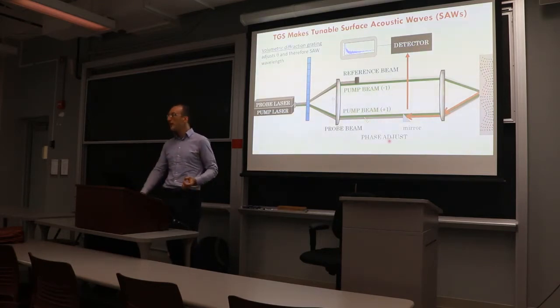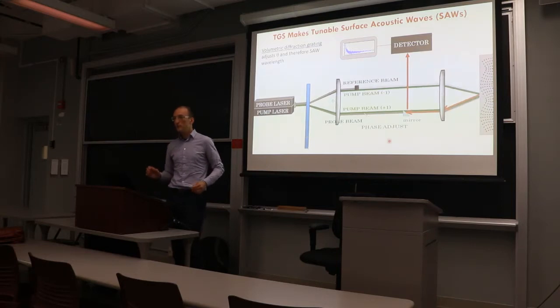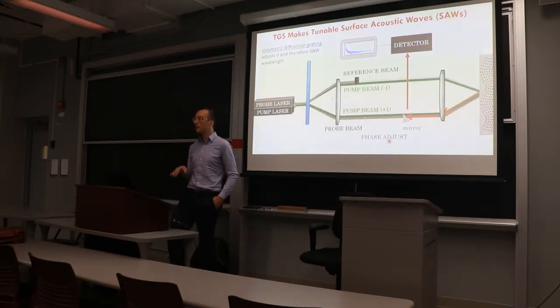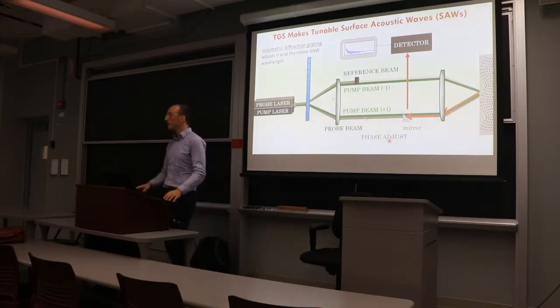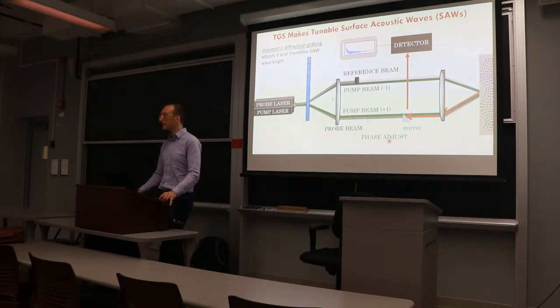So you want to interrogate that 1 to 10 microns, right? By changing the angle of attack of these lasers, you project a different transient grating spacing and elastically probe different 1 to 10 microns of the subsurface material. So a lot of people ask, is this a surface technique? And that depends on who you're talking to. If you're talking to a radiation person, the answer is no, it's a bulk technique, because what's happening 10 microns down is the same as what's happening 100 microns down. But if you go to 1 micron or less, then you've got surface effects to deal with.